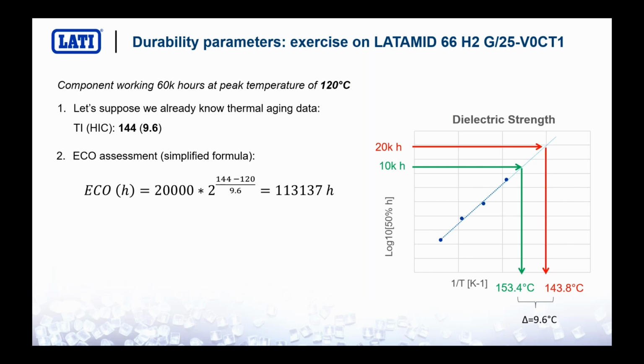Calculation says that this very material at 120 degrees will last more than 100,000 hours. Is this enough? Yes, because we wanted it to last 60,000 hours. So at the end of life, only 53% of its property potential will actually be depleted.